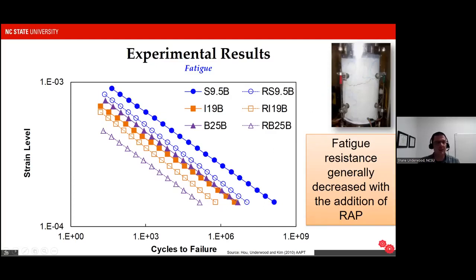What we clearly see when we look at fatigue is that at a given strain level, the non-wrap materials are actually performing quite a bit better. What this tells us is the material has stiffened when we added RAP, but it also became more brittle. If we take this material out into the field, and I'll show you some simulations in a moment, we might expect that the field performance is going to be degraded because that RAP-based material is more likely to crack under in-service repeated loading. And that pattern emerged for each of the different mixes. We see the surface mix was affected, the intermediate mix, and then the base mix, we saw a very big impact from these differences in fatigue performance.